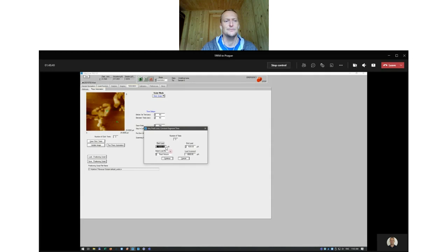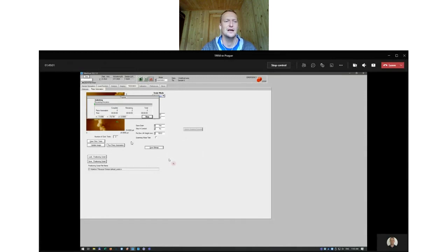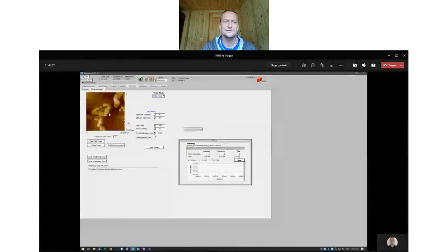So actually the first indent will be at hard phase, so I can use 5 millinewton force, let's say, and the other one will be in a steel matrix, so I can keep 1000 micronewton, so 1 millinewton force. So I just click continue, and now the piezo moves my tip to the first position here,